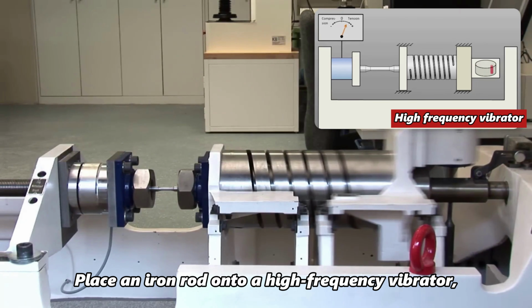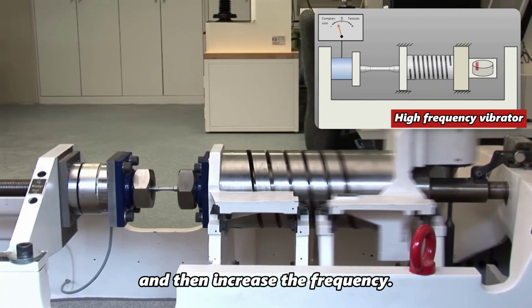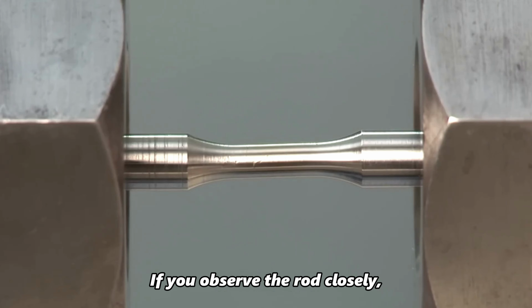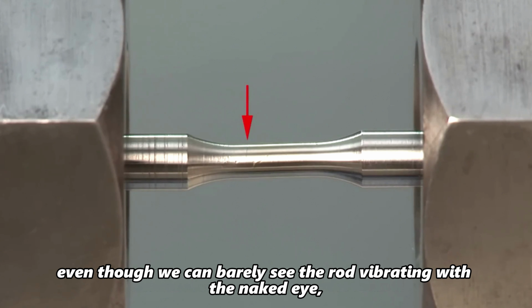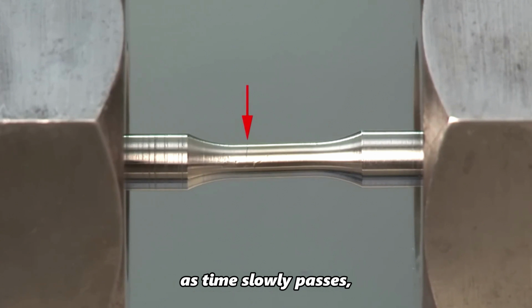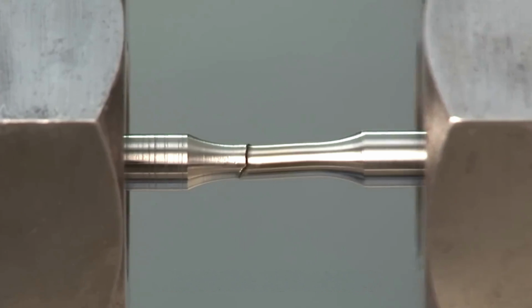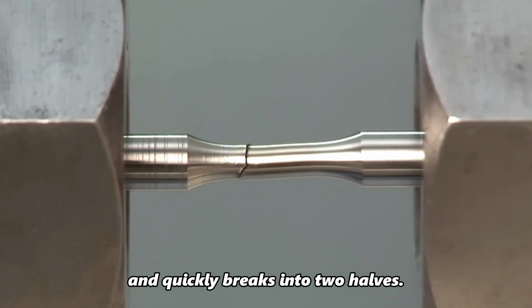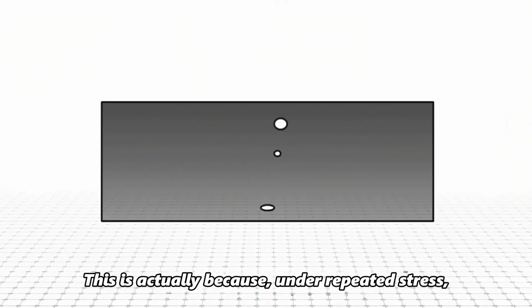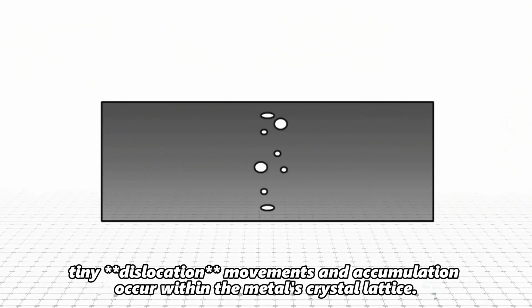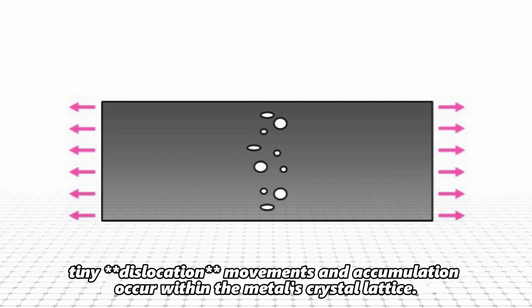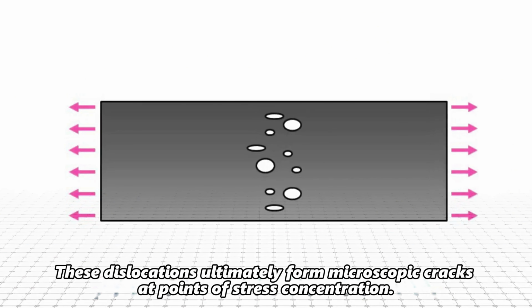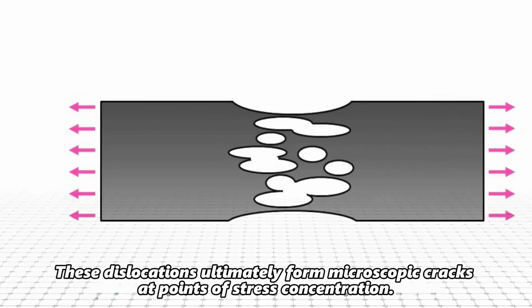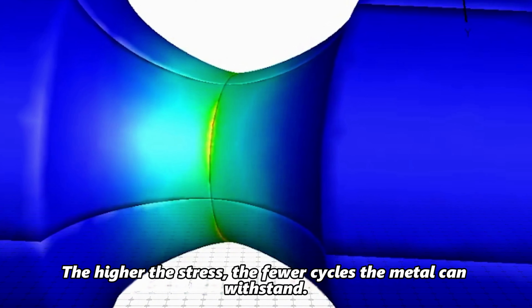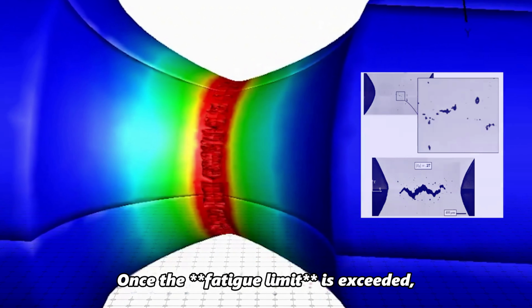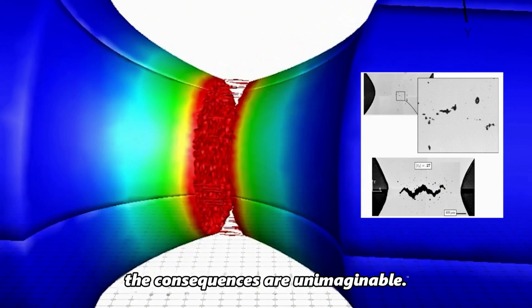Place an iron rod onto a high-frequency vibrator, and then increase the frequency. If you observe the rod closely, even though we can barely see the rod vibrating with the naked eye, as time slowly passes, a crack begins to appear in the middle of the rod. The crack grows larger and larger, and quickly breaks into two halves. This is actually because, under repeated stress, tiny dislocation movements and accumulation occur within the metal's crystal lattice. These dislocations ultimately form microscopic cracks at points of stress concentration. The higher the stress, the fewer cycles the metal can withstand. Once the fatigue limit is exceeded, the consequences are unimaginable.